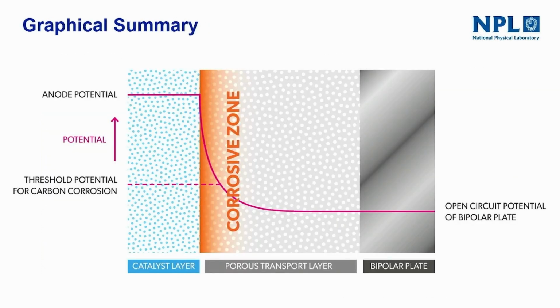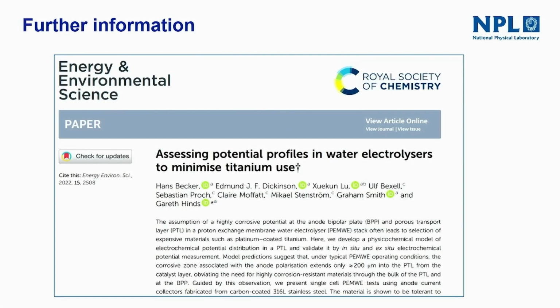So this summarizes graphically the high potential at the catalyst layer, the open circuit potential of the bipolar plate. It's not sitting at this potential, as everyone assumed prior to the work, and even we had to argue with world-leading electrolyzer scientists just to get this published. And the key thing is that through the porous transport layer, the potential drops like this because of the low conductivity of the deionized water in the pores. So I encourage you to have a look at the paper if you have time. It was published last year.